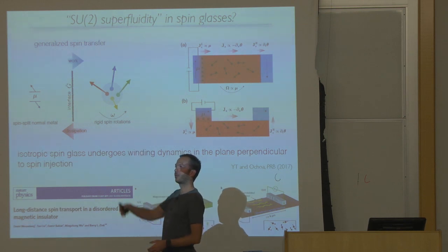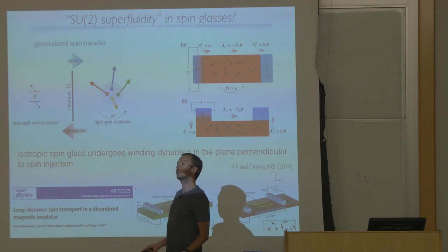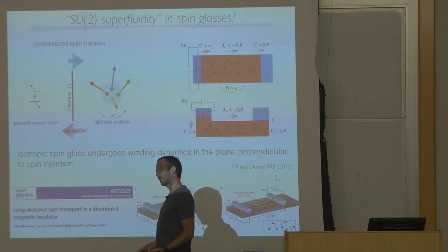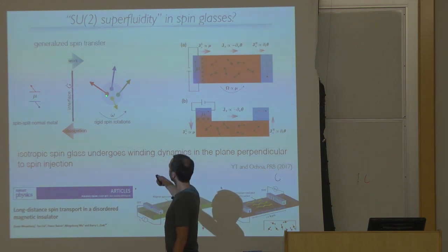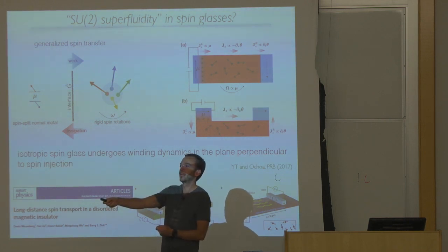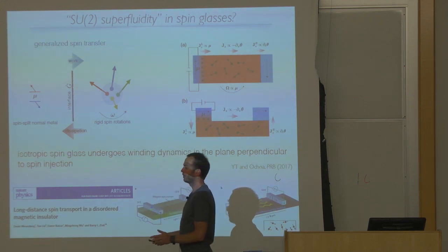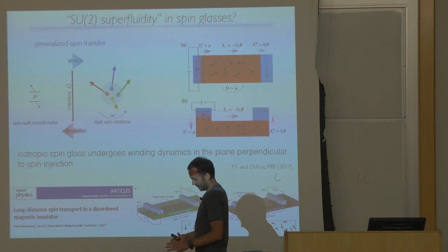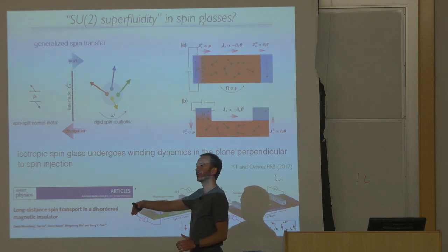Just like an amorphous material like a glass. There's no crystal order. But it's not a fluid, at least not on any reasonable time scales, because locally everything is frozen. So each local spin in the presence of its neighbors has some clear preferred orientation, and all other spins nearby also have preferred orientation. That means that at any given point, the system is frozen in a certain state, and its low energy excitations are kind of like phonons in a glass.